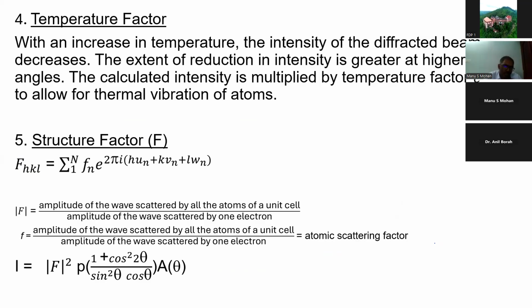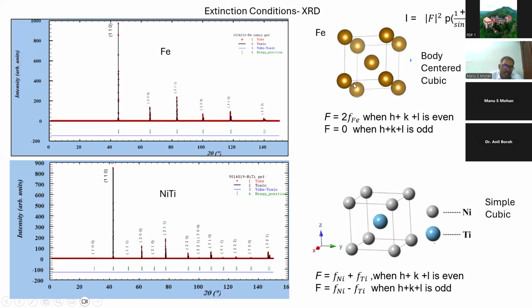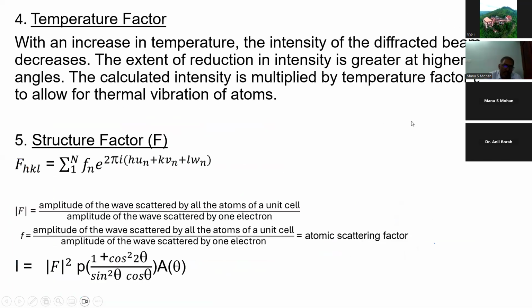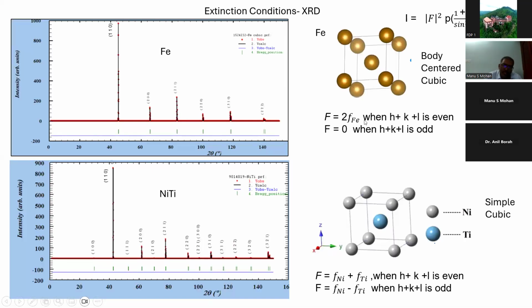So you have two coordinates now in body-centered cubic. This particular atom is showing 0,0,0, and the center atom coordinate is half, half, half. That is, if I move by x by half, y by half, z by half, I get into this position. So these two coordinates, if you substitute, you get e power 2 pi i, and if you expand it, you get the expression, and then you get two conditions: f equal to 2fe when h plus k plus L is even, f equal to 0 when h plus k plus L is odd. So what is the significance in the pattern now?